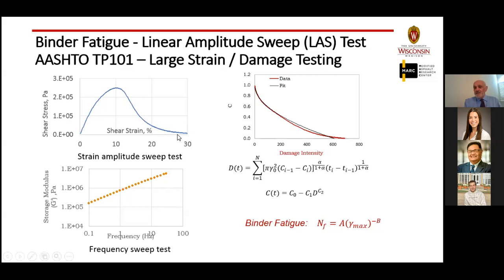Instead of using the simple procedure you have in the LAS, we looked at the post-peak slope and the area under the curve, and we selected the viscoelastic continuum damage. Some of you recognize this equation, where you look at the damage intensity and how it changes with C, and C is just a relative modulus. So modulus versus damage gives you an imprint of how the fatigue is progressing in any material using the continuum damage. But out of this comes a very conventional equation that we all recognize, which is a fatigue law.